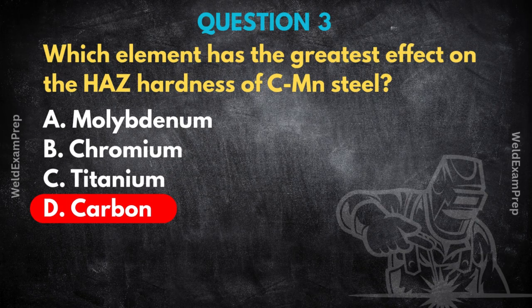Well, carbon is fundamentally the primary hardening element in steel, full stop. Now, when you weld, that area right next to the weld metal, the HAZ, goes through a really rapid heating cycle, followed by quite rapid cooling as the heat dissipates into the surrounding metal. Right, that thermal shock. Exactly. And this rapid thermal cycle transforms the microstructure of the steel in the HAZ.